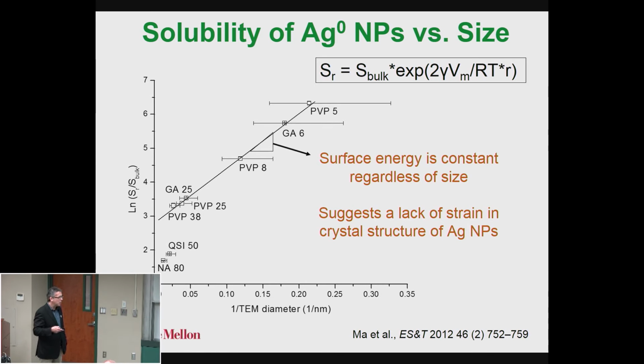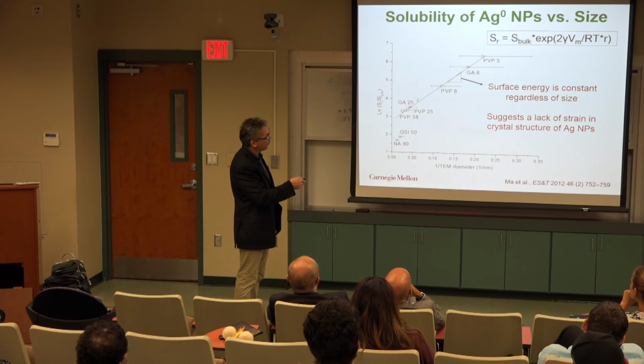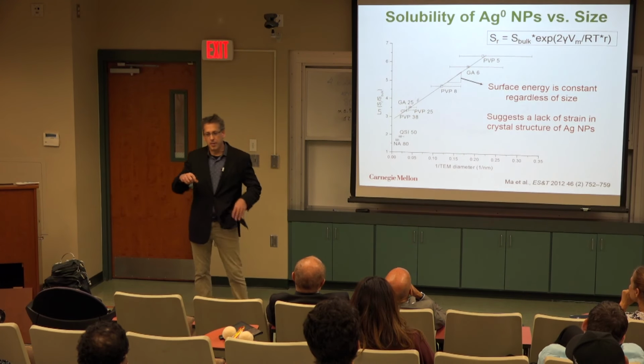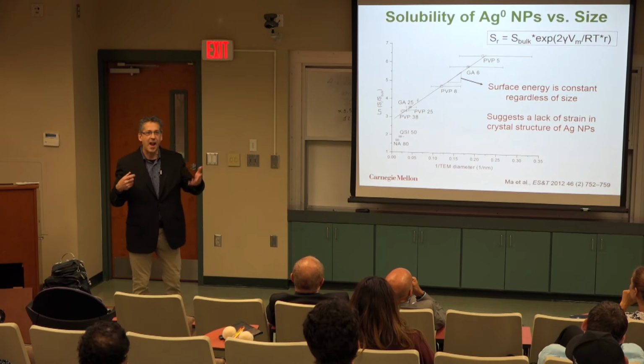Okay, that was interesting. But then when you model it with this Ostwald equation, you get a surface energy. And don't worry about all the details, but this is the diameter of the particle, so the solubility is a function of diameter. But here's the surface energy. That tells you something about the stress and the strain on the material and how reactive it would be.